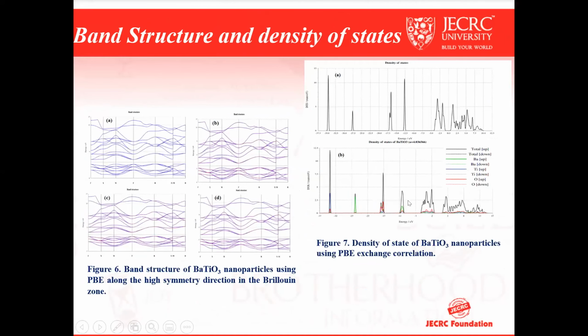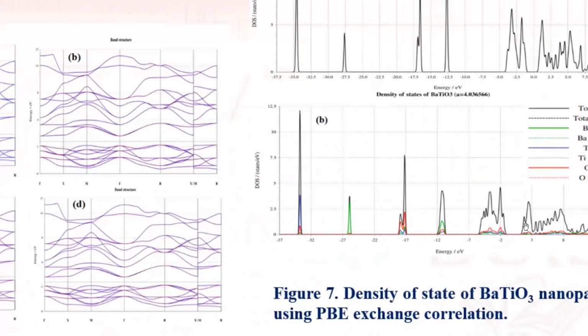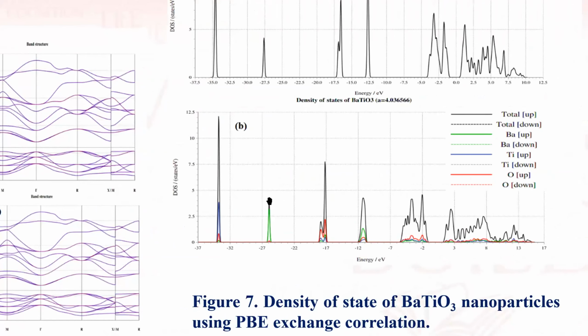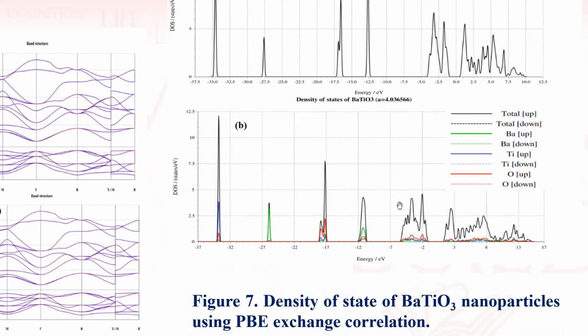diagram, that is the density of states versus the energy. So here also we are getting two bands, which are the valence band and conduction band. The conduction band is from 0.5 electron volts to 17 electron volts in this region, and the valence band is from minus 37 electron volts to minus 1.5 electron volts. And we have also found that in between this conduction and valence band there are no intermediate lines. That indicates that it is an energy gap, and this is what the band gap actually is.